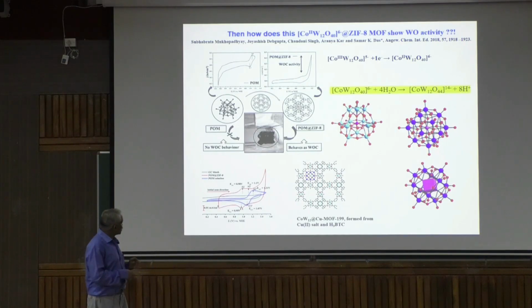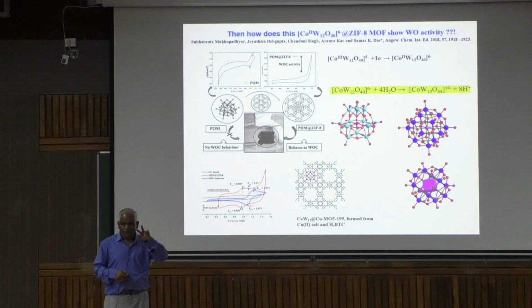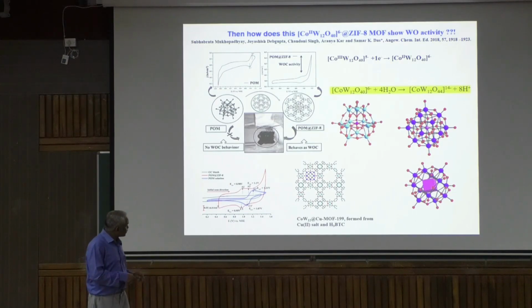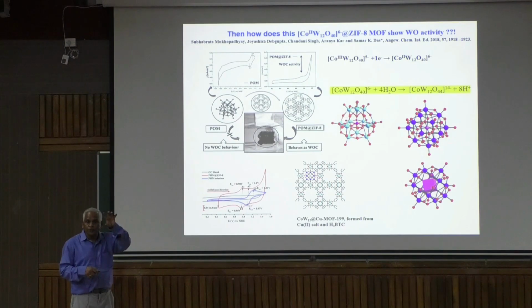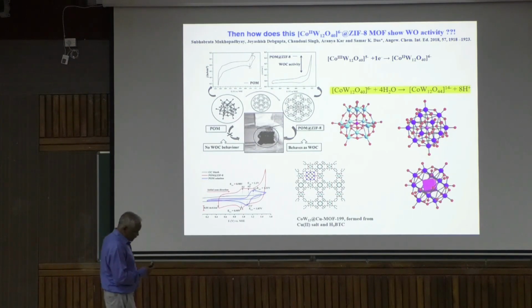I mean, let's say these tetrahedral oxygens are disordered over 2 positions. If one oxygen is half occupancy, disordered over 2 positions, it will look like it is octahedral. But in this case, we checked 2-3 times again, we measured the crystal, and we got full occupancy of each oxygen. It really is a cube of 100. I mean, a cube, with cobalt in the center. That means if chemistry has to happen, it will hydrolyze.